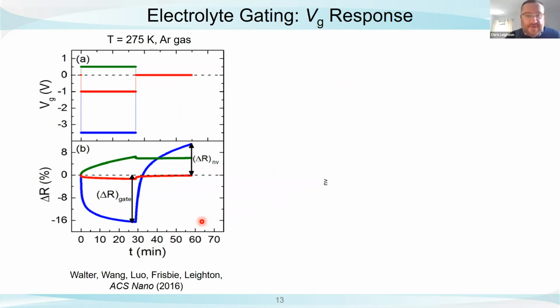So this is the simplest kind of experiment one can really do. We're sitting here just underneath room temperature. We are in an inert gas, argon. We're applying voltages. They could be positive or negative. And we're measuring the resistance change of the device. So here the ions are mobile and we can measure a time response. So if we apply a negative voltage, we get exactly what we expect. So -1 volt, this material's hole doped. You apply a negative voltage, you should accumulate more holes. So the resistance should drop, it should saturate, and then when we turn the bias off, it should go back to exactly where we started.